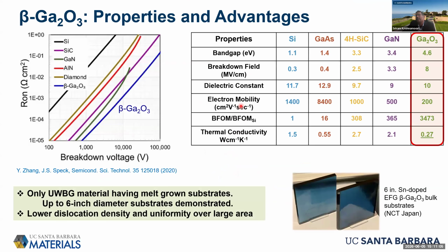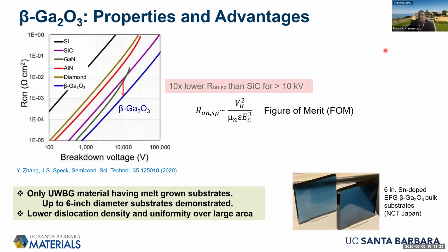And this is where gallium oxide gets exciting, because gallium oxide has a bandgap of 4.6 electron volts, much larger than silicon, and a bit larger than gallium nitride and silicon carbide. One exciting aspect of this material is that we actually have bulk substrate technology available. These are 6-inch edge-defined film-fed grown, melt-grown substrates from Japan. You can buy 4-inch substrates off the shelf even today, and 6-inch would be a special order.